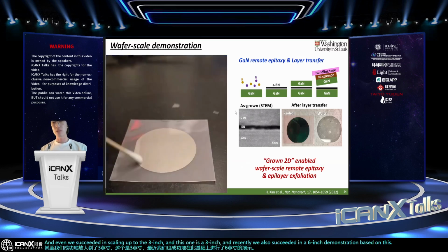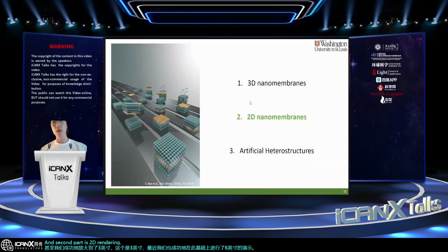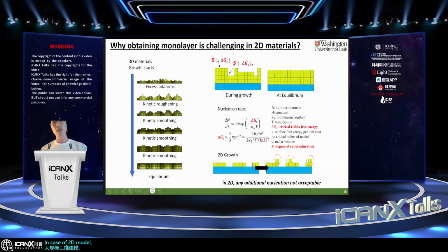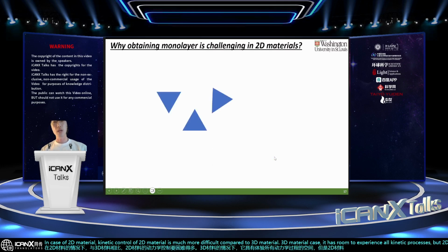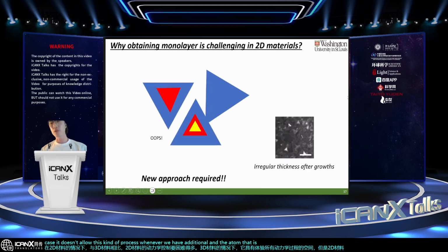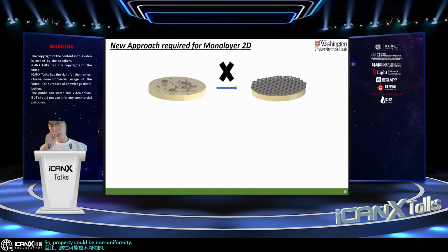The second part is the large scale 2D material case. In the case of 2D material, kinetic control is much more difficult compared to 3D material. In the 3D material case, it has room to experience all the kinetic processes, but the 2D material case doesn't allow this kind of process. Whenever we have an additional atom, it turns out to be irregular 2D material, so the property could be not uniform. So what we thought is that getting a monolayer by growth is extremely challenging.